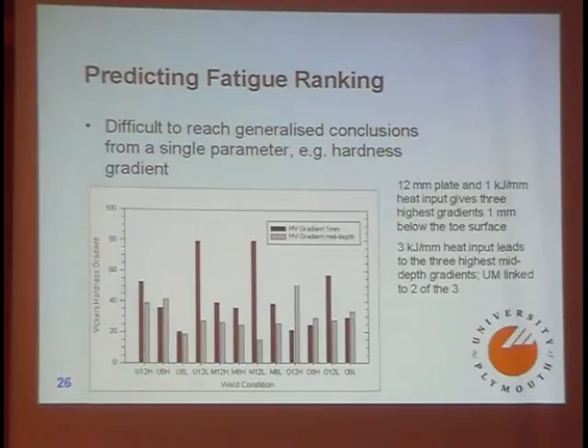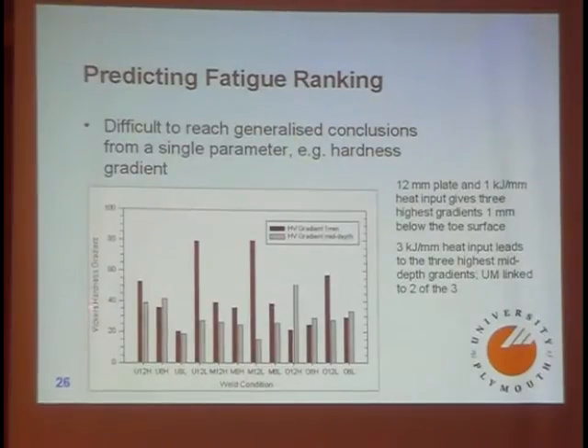And if you consider a single parameter like hardness gradient, you don't get terribly far. These are hardness gradients against weld conditions, and it's difficult to make sense of that. Your 12 plate and the low heat input give the 3 highest gradients at 1 millimeter, but the 3 highest mid-depth gradients come elsewhere.